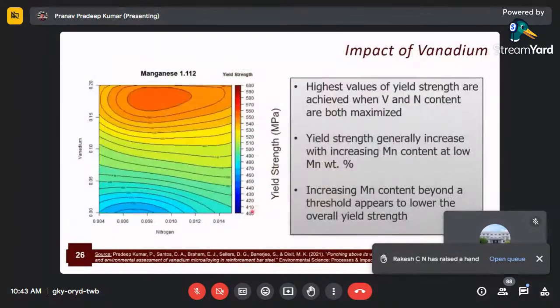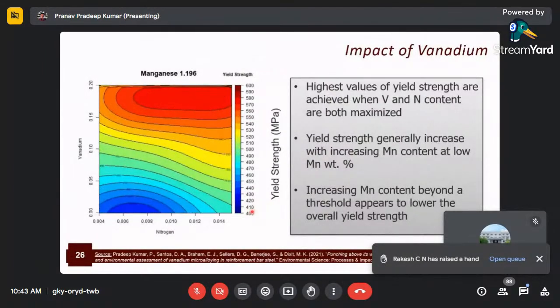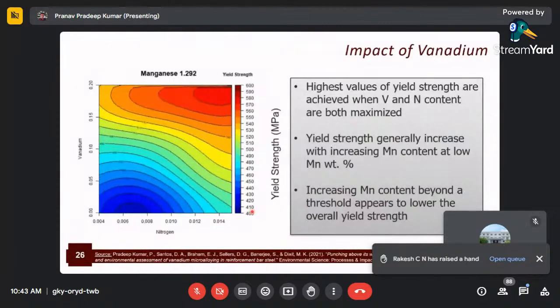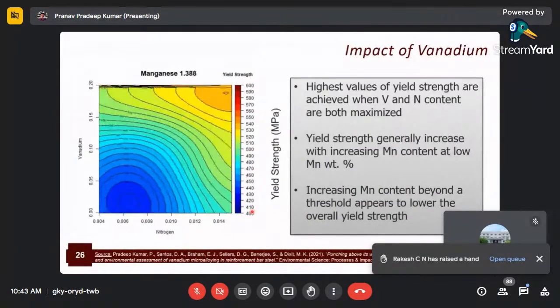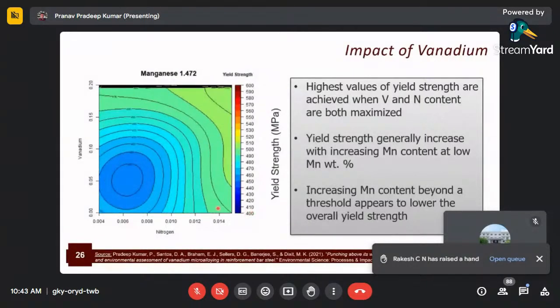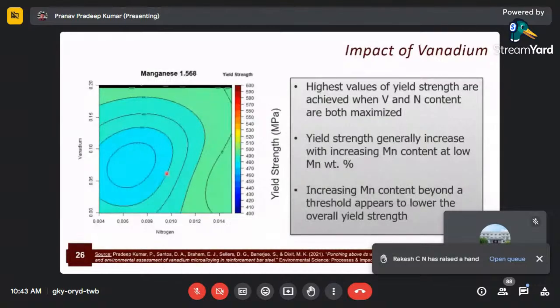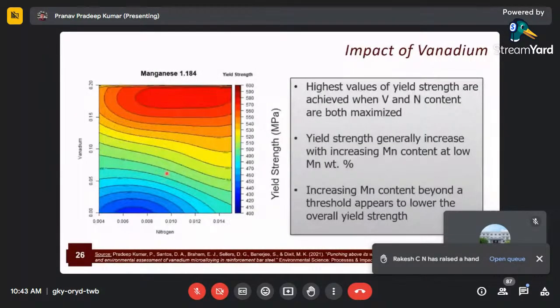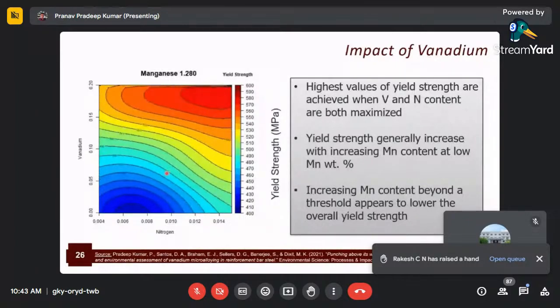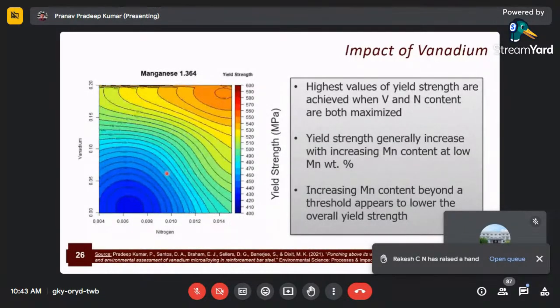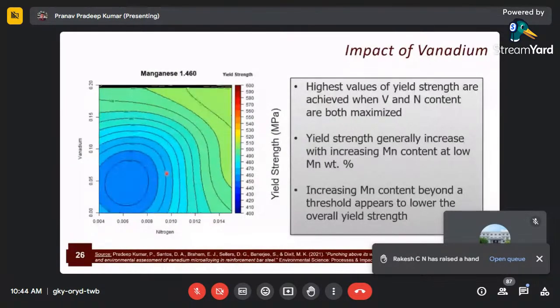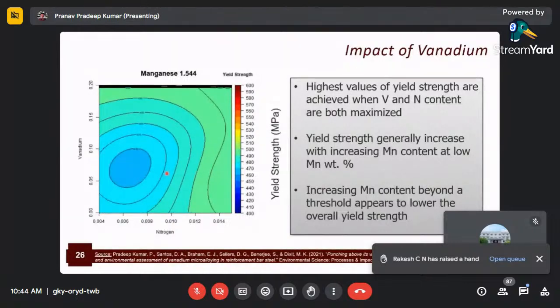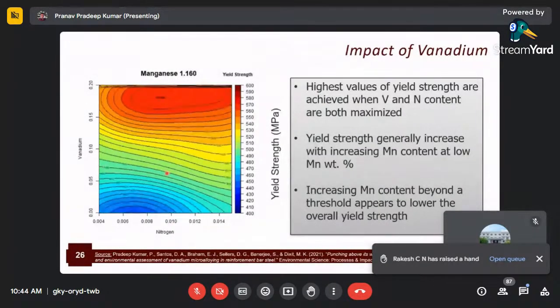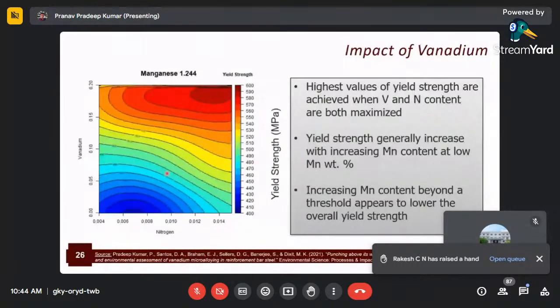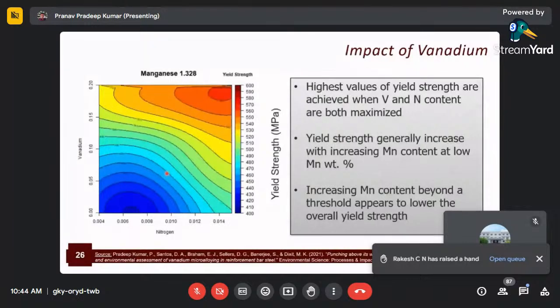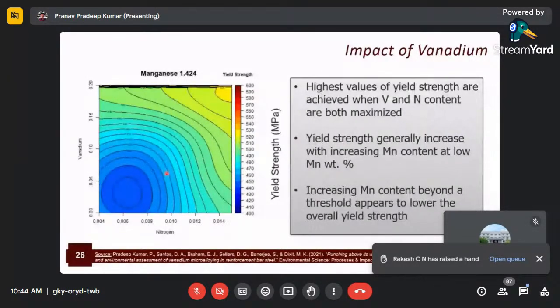And here I'm just showing the model that we prepared using machine learning. Here we can see how the change in vanadium content influences the yield strength of the steel. From this plot, we can see that there are three components that primarily impact the yield strength: nitrogen, vanadium, and manganese. The highest values of yield strength were observed when the vanadium and nitrogen content was maximized, while the yield strength generally increases with increasing manganese content, but only up to a value of about 1.2 weight%. After that, there's a threshold value beyond which the yield strength of steel reduces. Using this model, we obtain the percentage of vanadium that's required to generate a particular grade of steel.